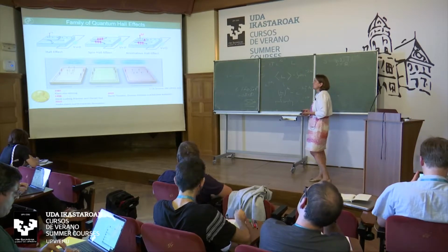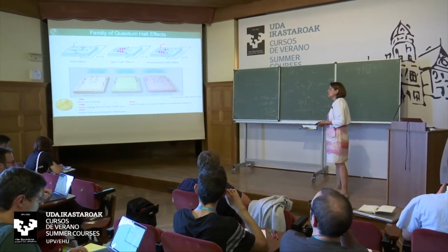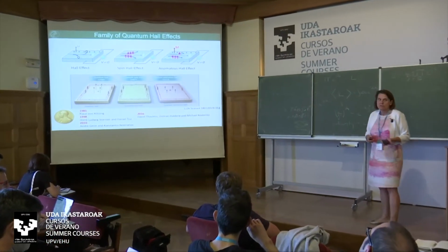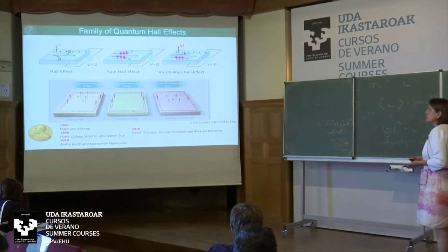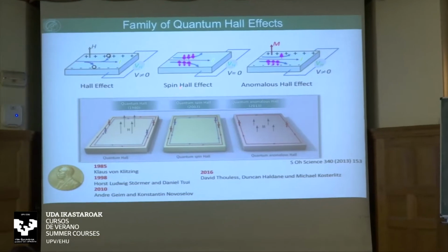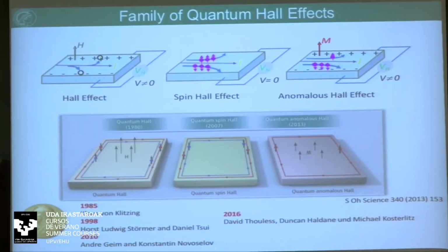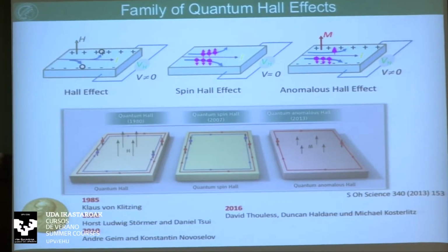And most of our measurements are classical measurements, so different from what you heard about the quantum spin Hall system, mercury telluride already. So we measure bulk materials, so we measure the Hall effect, so we measure the transport by applying a magnetic field, and we get information like the mobility, the charge carrier type, etc.